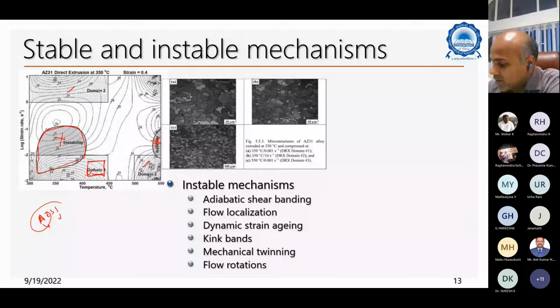What happens is, let's take one such alloy, AZ31 alloy. I'm doing this operation at two temperatures: 350 and 550 degrees centigrade. At 350 degrees centigrade, I'm using two different velocities. I'm striking this sample, which I kept in between the two anvils. So when you do that at 0.001, in domain 1, you get a microstructure like this.